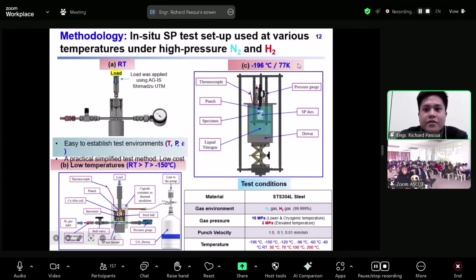As you can see, these are our various test setups in different temperature conditions under a high pressure nitrogen and hydrogen gas environment. At room temperature, we simply expose the material to ambient temperature during the test. The load was applied using the universal testing machine. At lower temperature,